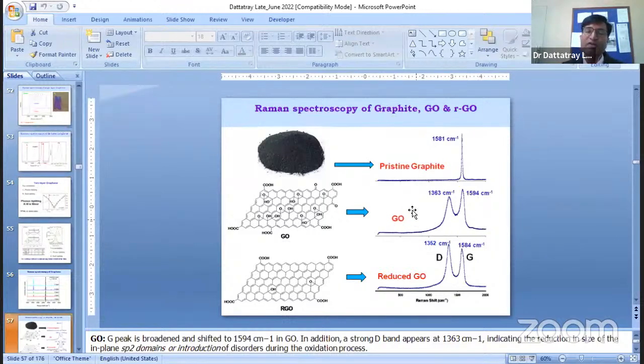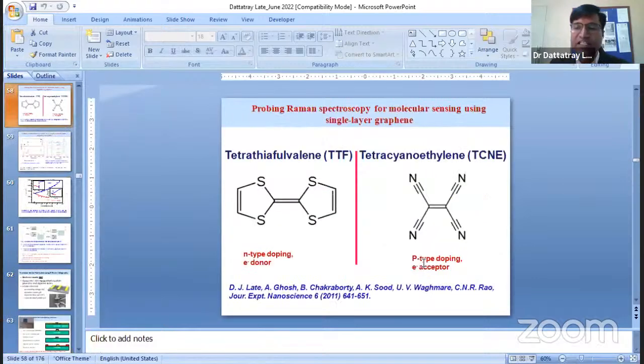And the moment you convert this graphite oxide into reduced graphene oxide, you see the intensity of this defect D band, here the intensity ratio D by G, which is larger. So you have already reduced many of these groups, and you have actually a reduced graphene oxide, right? So these are some of the simplest techniques to identify this kind of material, right?